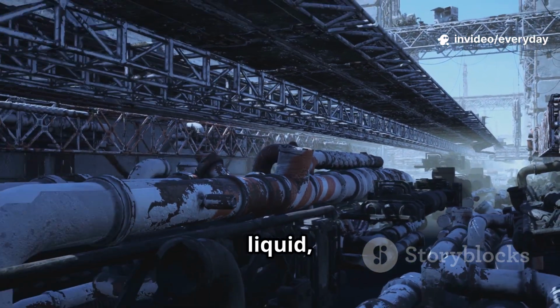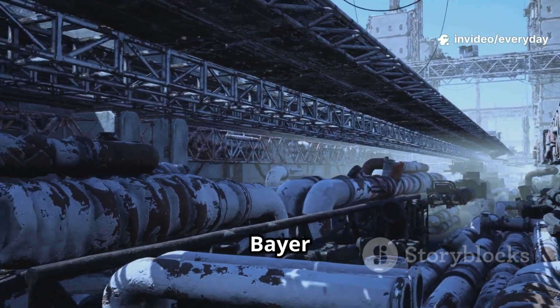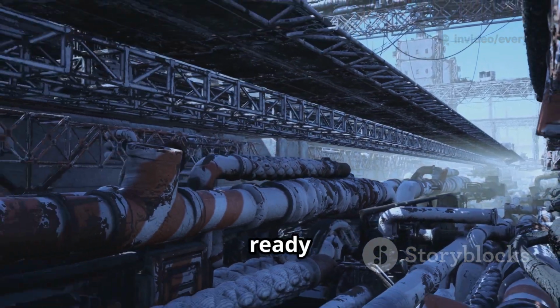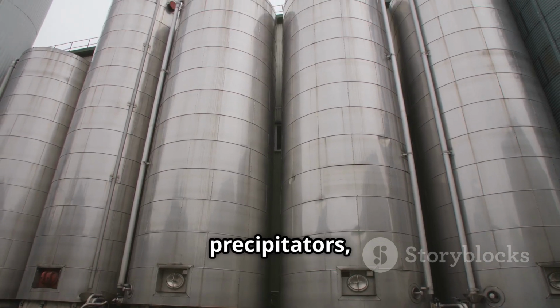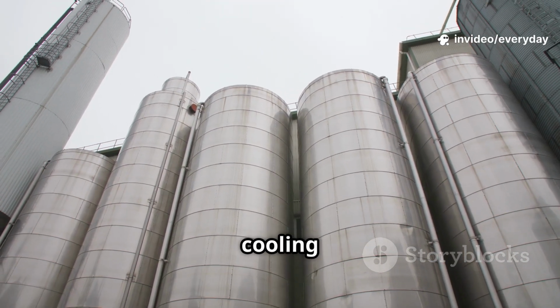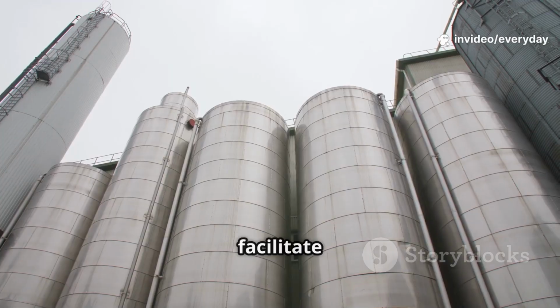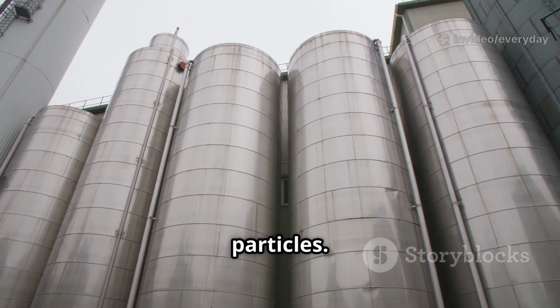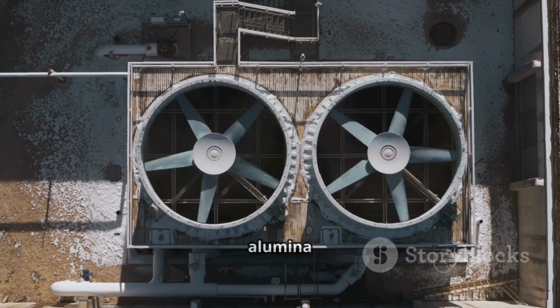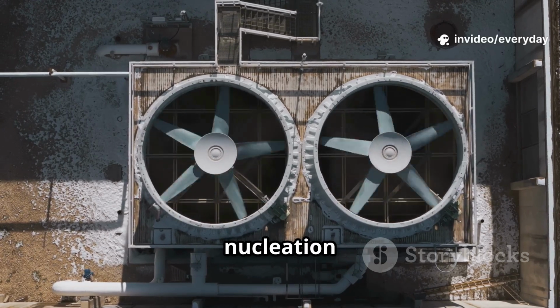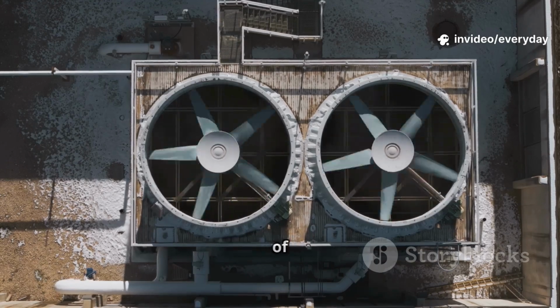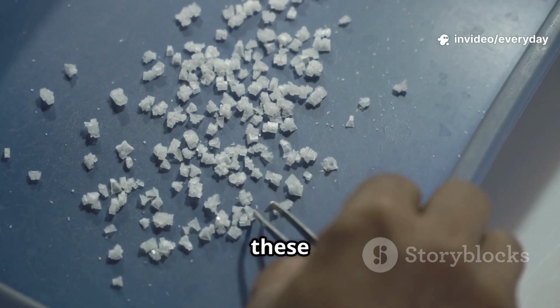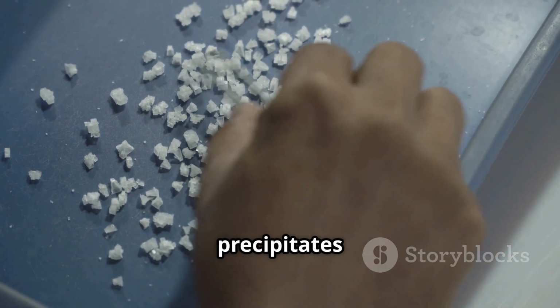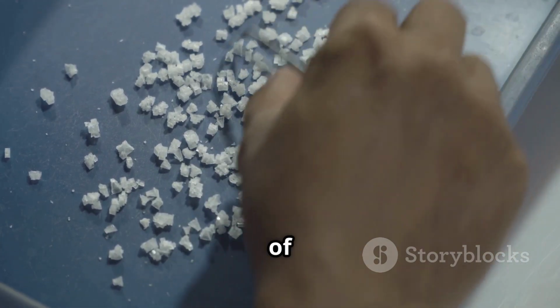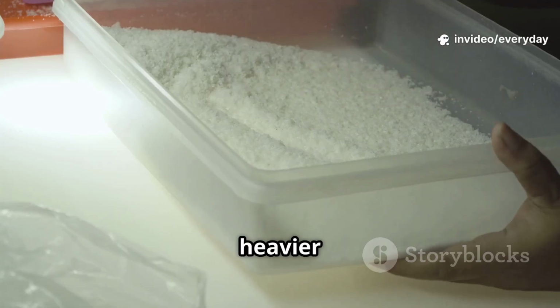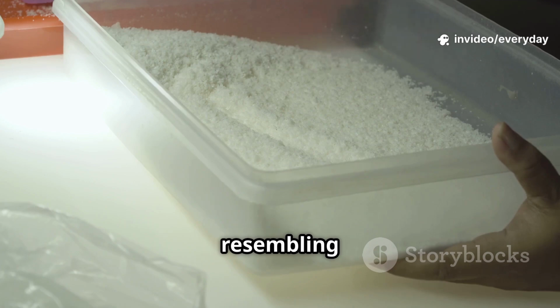Meanwhile, the alumina-rich liquid, now free of impurities, moves on to the next stage of the Bayer process. It flows through a network of pipes ready for further refinement. In tall tanks called precipitators, the alumina solution undergoes a controlled cooling process. These towering vessels are designed to facilitate the formation of solid alumina particles. As the solution cools, tiny seed crystals of alumina are added. These crystals act as nucleation sites, encouraging the dissolved alumina to precipitate out of the solution. Pure alumina begins to form around these seed crystals, growing in size as more alumina precipitates from the solution. This is a beautiful example of controlled crystallization. The alumina crystals, now heavier than the solution, begin falling to the bottom of the tanks, resembling a gentle snowfall.